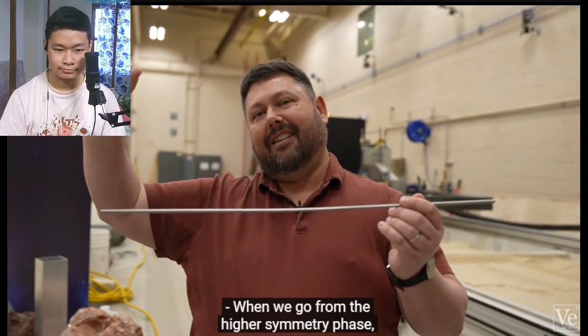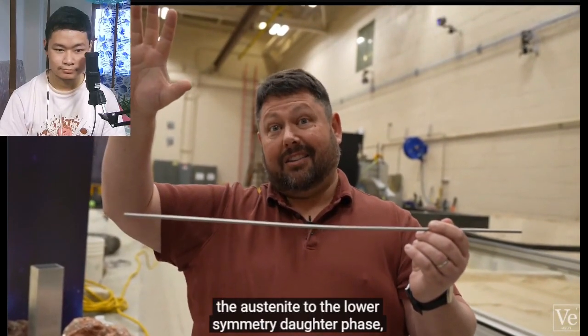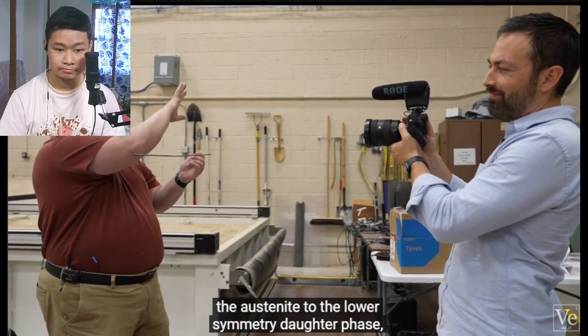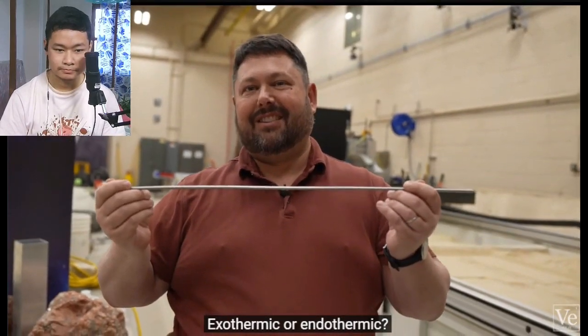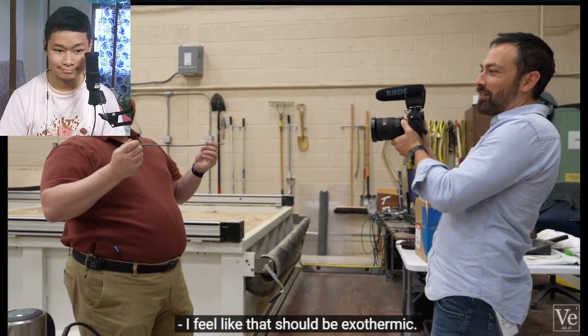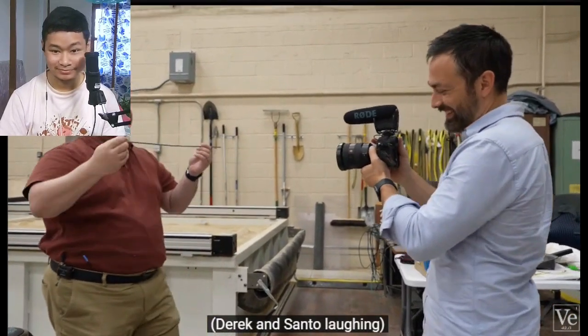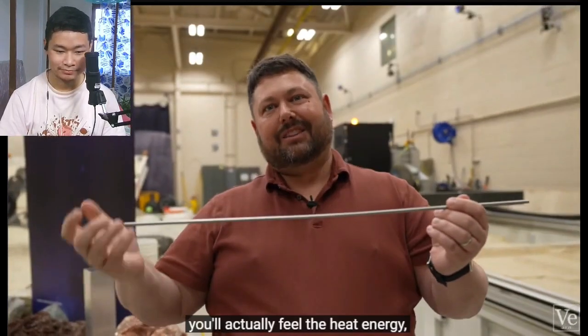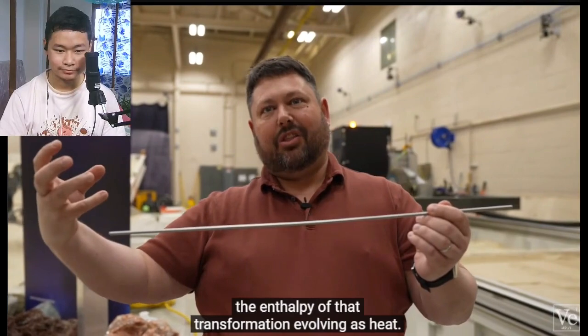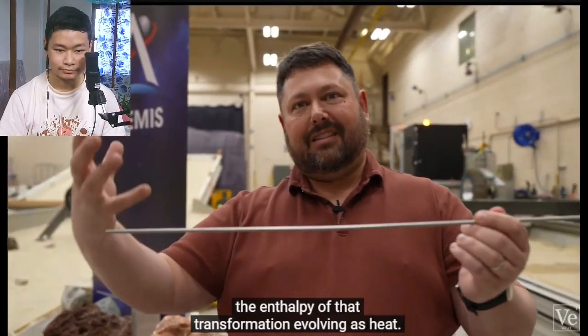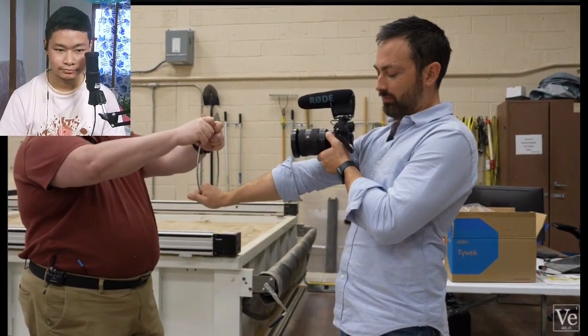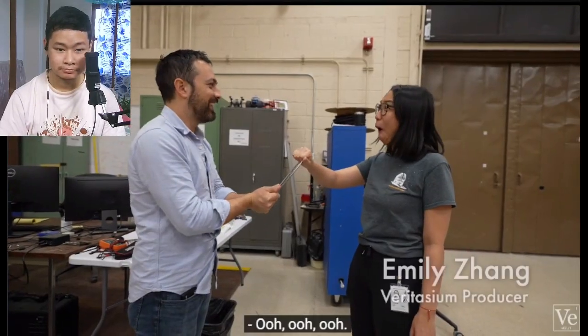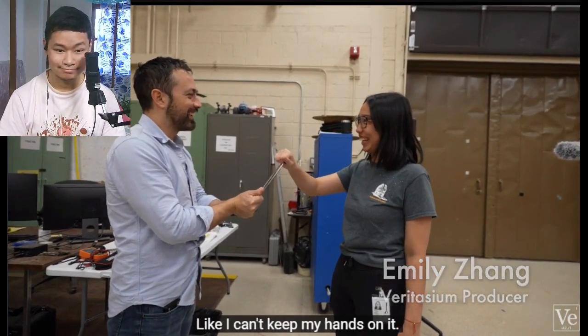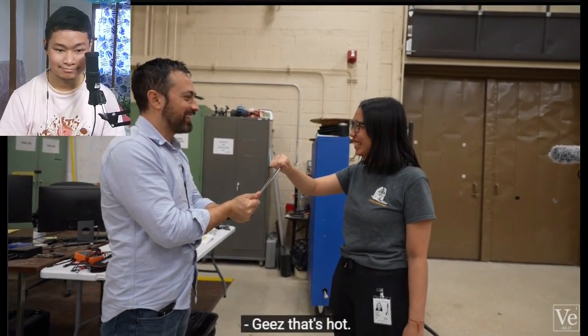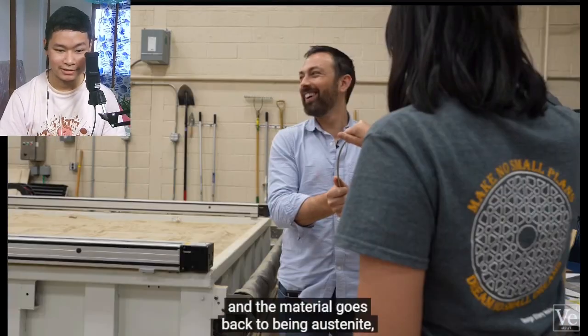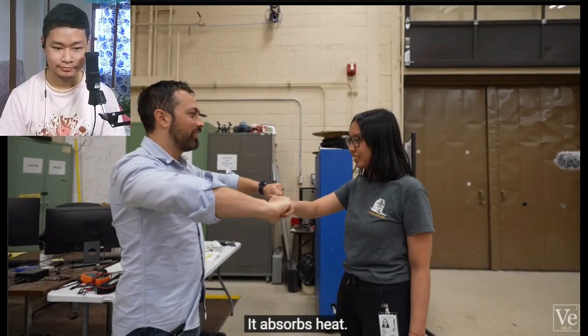When we go from the higher symmetry phase, the austenite, to the lower symmetry daughter phase, which one is it? Exothermic or endothermic? I feel like that should be exothermic. Good job, science guy. If you were to put your hand around this tube, you'll actually feel the heat energy, the enthalpy of that transformation, evolving as heat. You ready? Yep. Oh yeah, that's real hot. That actually is like burning. I can't keep my hand on it. It won't burn you. When the stress is removed and the material goes back to being austenite, that phase change is endothermic. It absorbs heat.